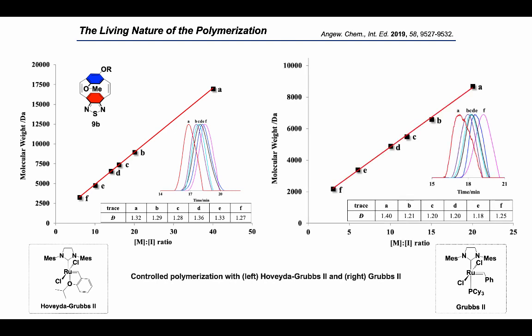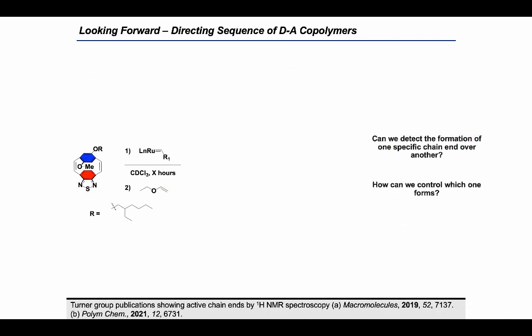Trials using Grubbs 2 demonstrated effectively the same trend, which helps further confirm that we're able to achieve the first synthesis of a donor-acceptor PPV by living polymerization techniques. While this was all exciting, promising, and answered the question of if we can even make these materials, we still need to address and answer the question of how to control the sequence of this alternating copolymer.